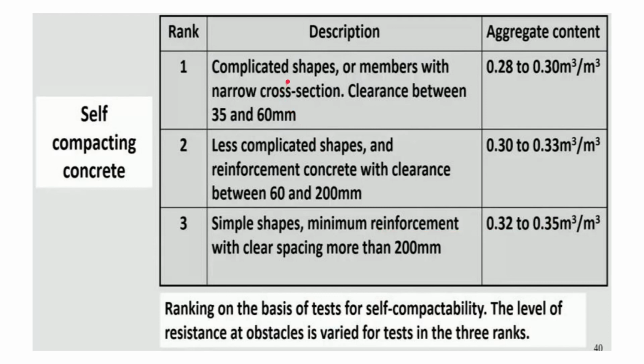If the shape is very complicated and members have a narrow cross section, and the clearance of reinforcement is between 35 and 60 mm, which is very less, then we have to further reduce the aggregate content to 0.28 to 0.30 meter cube per cubic meter of concrete. But if the complicated shapes are less and the clearance of reinforcement is increased from 60 to 200 mm, then we can increase the aggregate content from 0.3 to 0.33 meter cube per cubic meter of concrete.